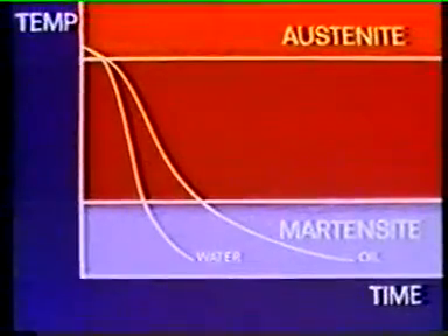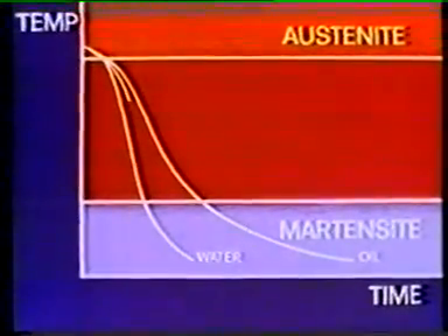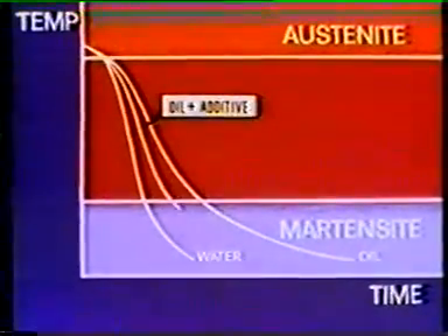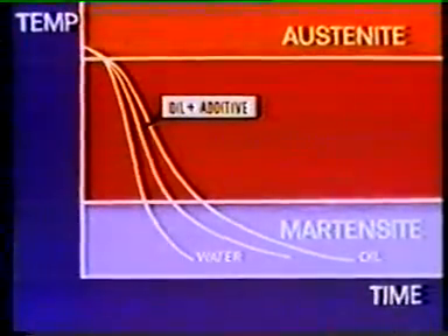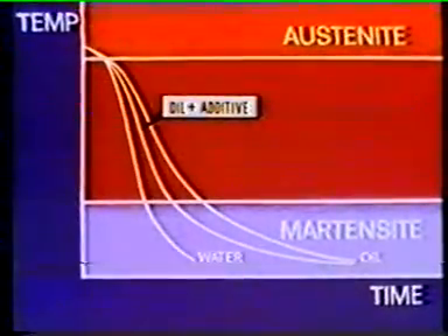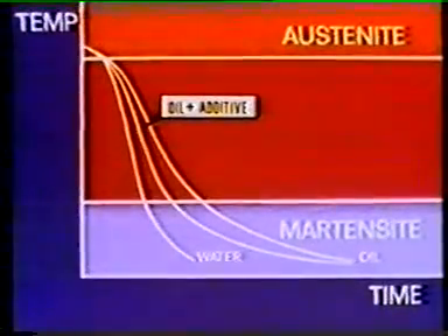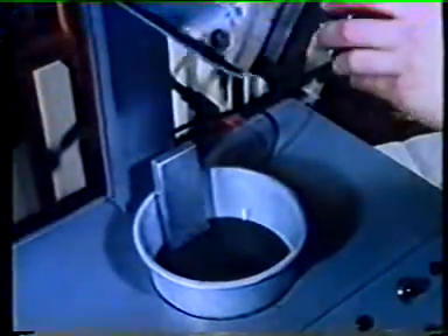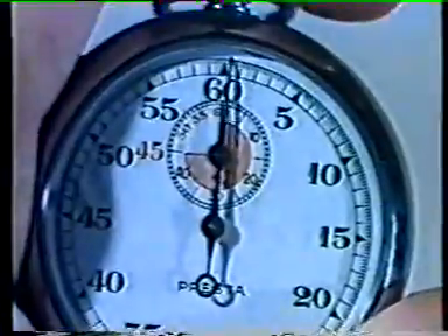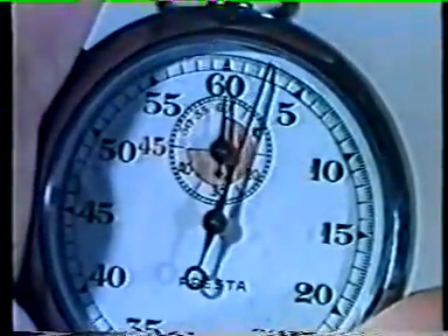Meantime, research goes forward into means of extending the range of quenching oils by the use of additives. Again, the result may be seen on our graph. Rate of cooling is faster in the initial stages to avoid transformations, but it slows down like that of ordinary quenching oil at the lower temperatures when hardening takes place. Accelerated quenching oils can be used to quench lower carbon steels without cracking them, or to obtain greater depth of hardness in more expensive steels.